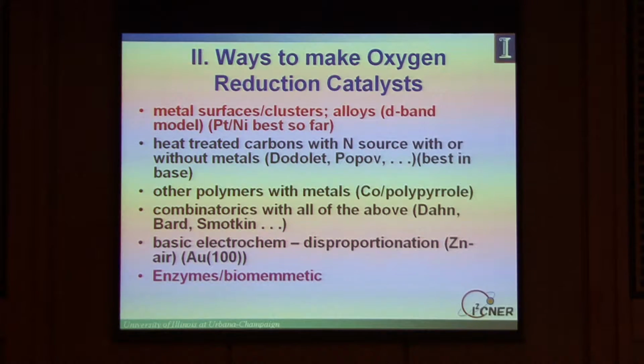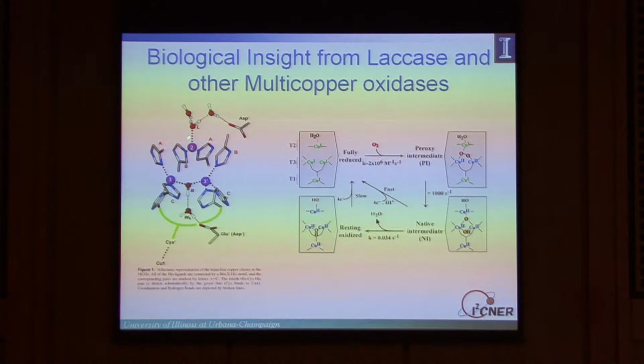And finally, we can look to what nature tells us. And it's this point that I want to emphasize here. So it turns out nature has solved the oxygen reduction reaction problem. All right? Nature does this. In fact, right out there, right on the ground out there, there's an enzyme called laccase, which is right away now reducing oxygen at near thermodynamic potentials, and it uses that energy to oxidize various things. All right? What it features is a 3-copper active site right here, and a series of intermediates that are not dissimilar from what I very quickly glanced over before.